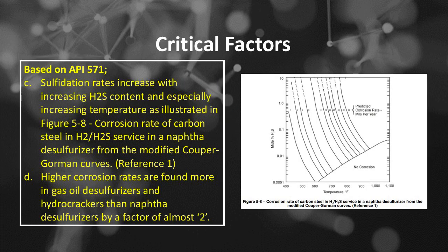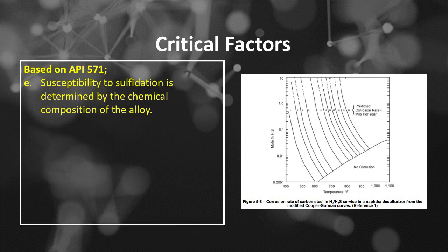Number C, sulfidation rates increase with increasing hydrogen sulfide or H₂S content and especially increasing temperature as illustrated in Figure 5.8, corrosion rate of carbon steel in hydrogen or H2 or hydrogen sulfide or H₂S service in a naphtha desulfurizer from the modified Couper-Gorman curves. Number D, higher corrosion rates are found more in gas oil desulfurizers and hydrocrackers than naphtha desulfurizers by a factor of almost 2. Number E, susceptibility to sulfidation is determined by the chemical composition of the alloy.